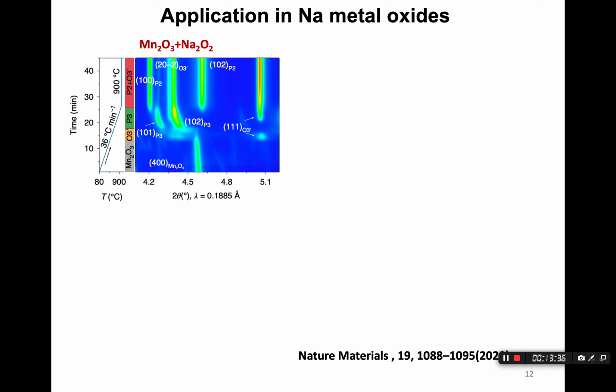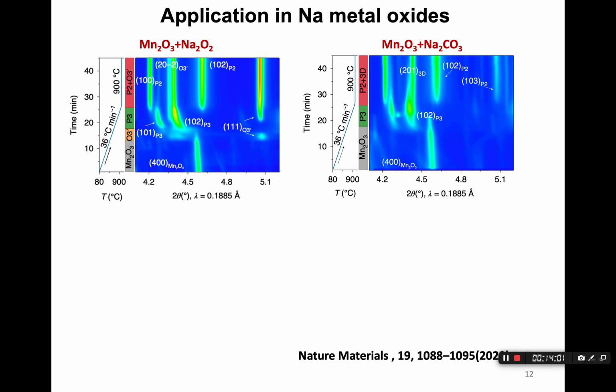So, going back to some real computation data, we can also apply this to other sodium metal oxides, for instance sodium manganese oxide. Usually we use manganese oxide mixed with sodium peroxide. In that case, you're going to form a metastable O3 prime phase, which is similar to sodium cobalt oxide. And if you mix that with sodium carbonate, you will never see the O3 prime phase, as derived from the in situ XRD experiment.